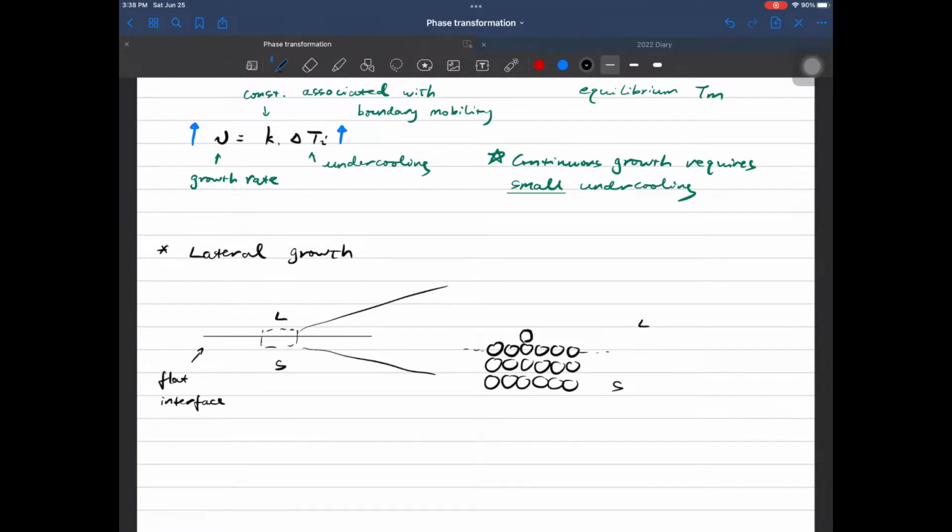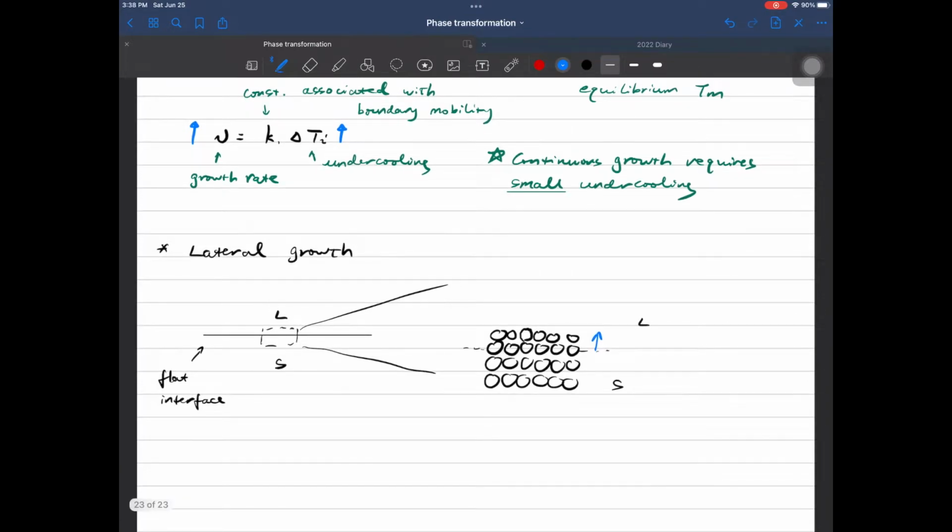During the growth process, one atom solidifies on the surface. Because of the dangling bond, as well as to minimize the surface energy, the atoms will adhere on the new surface and grow laterally. This advances the liquid-solid interface by one atomic layer, and this process is called lateral growth.